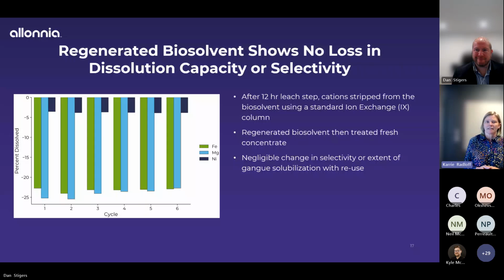What we've been able to see is that our regenerated biosolvent is showing no loss in capacity in how much it's removing, or in the selectivity when it's doing that removal. These are 12-hour leach steps, and we're stripping out the cations using just a standard IX resin. We see a negligible change in the selectivity of how much magnesium is being removed in each of the 6 cycles, how much iron is being captured with that, and that the nickel loss is constant. Each one of these cycles is the same biosolvent having passed through the IX, treating new concentrate.